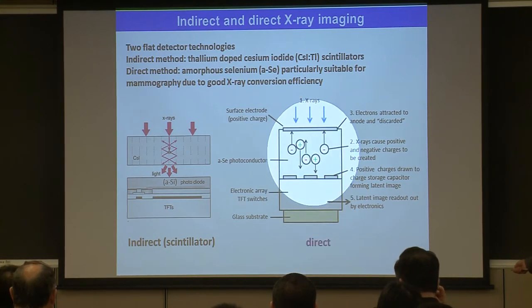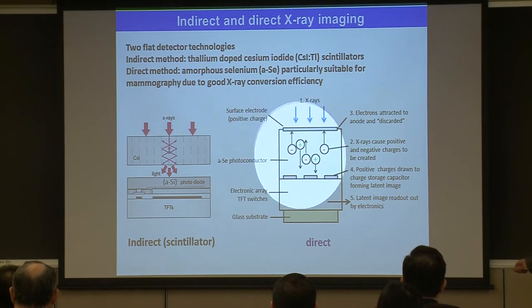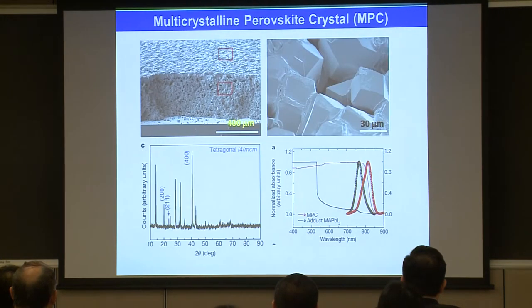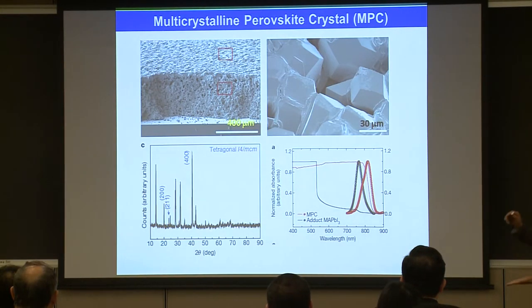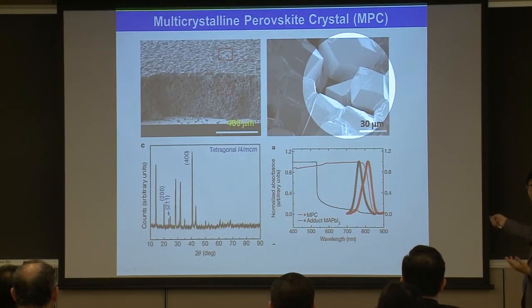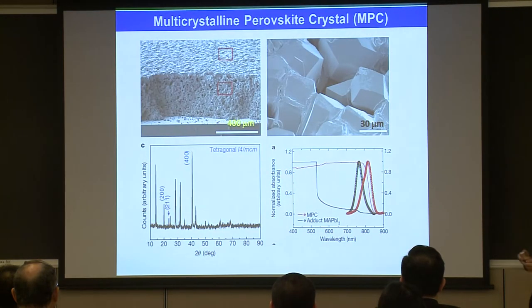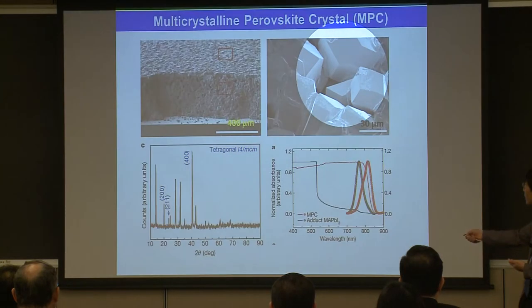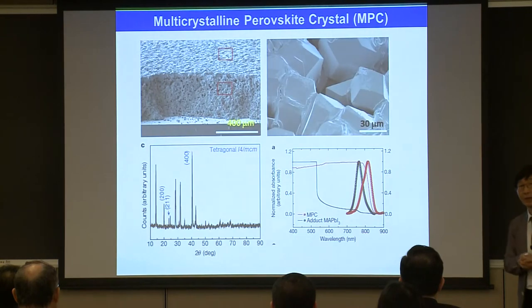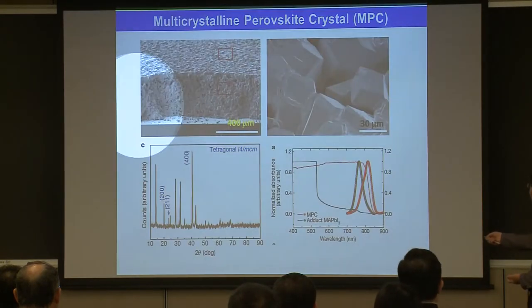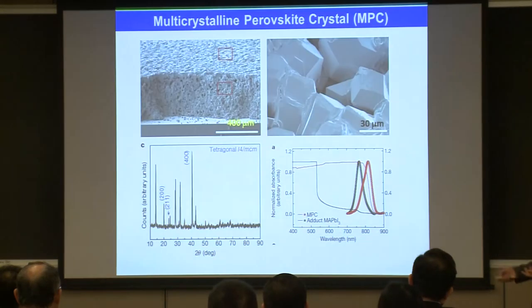Using the direct method, we prepared a thick perovskite layer, which is deposited directly on the TFT backplane. In that case, we need some very large crystal because the layer thickness for this photo detector is around 1 millimeter, meaning 1,000 micrometer. So in order to get a very thick layer, you need very large crystals. We actually succeeded in making large crystals. One grain is about 30 micrometer, and then we deposited this multi crystal to make a thick film, and by a pressing treatment, this film looks like single crystal behavior when you measure the UV visible spectrum.